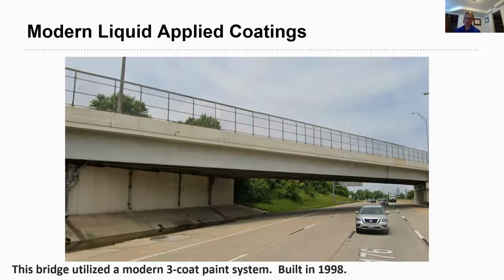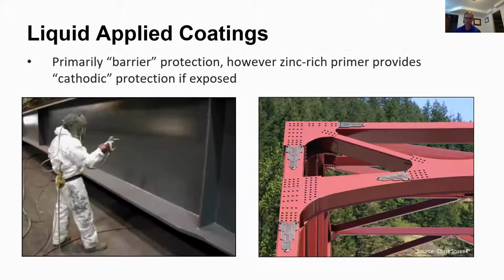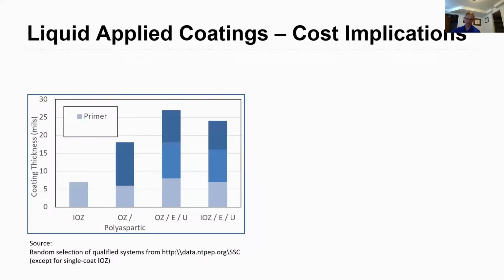And so you can see that it still looks to be in good shape today with no evidence of any sort of corrosion forming there. So this is the modern corrosion protection system. So this is what I would encourage you to think of when you think of paint systems. Typically, these are barrier systems. However, the zinc-rich primers do provide some cathodic protection if it's exposed. So if the intermediate and the top layer, if it's a 3-coat system, do get deteriorated, for example, and the zinc-rich primer is exposed, then it will provide some cathodic protection as well.